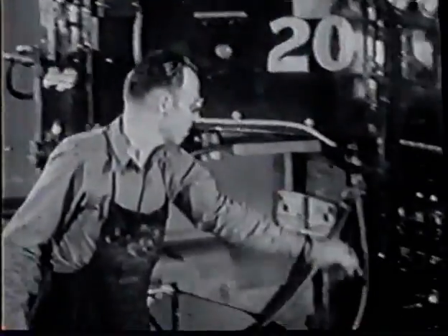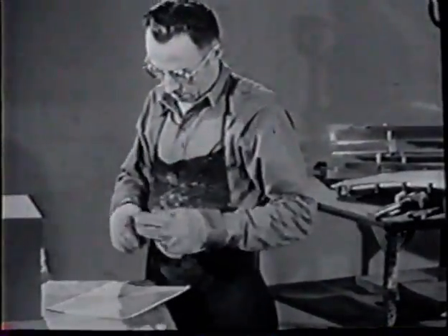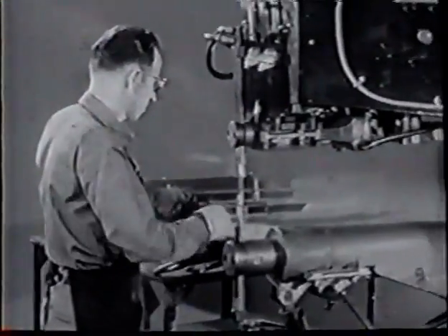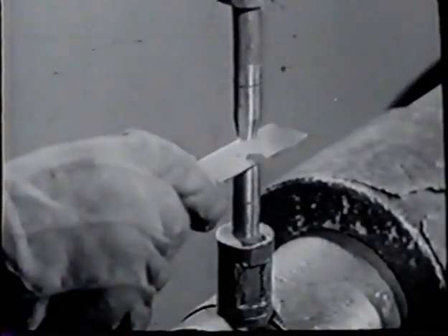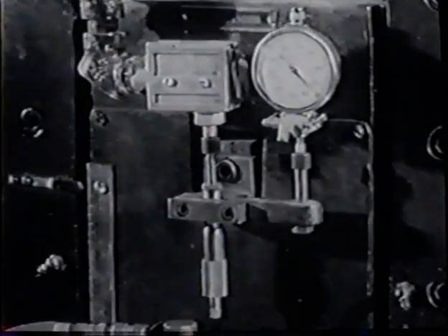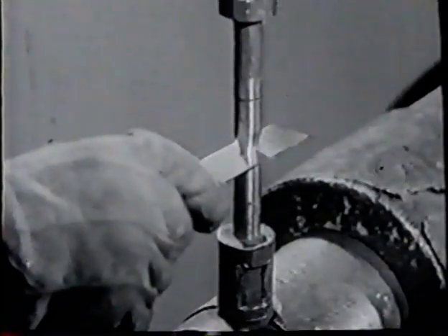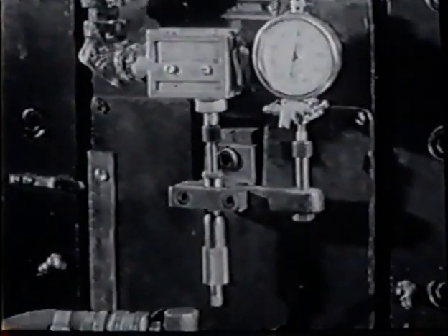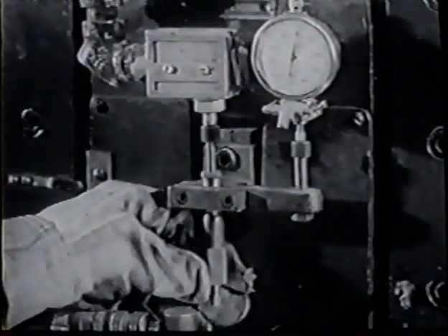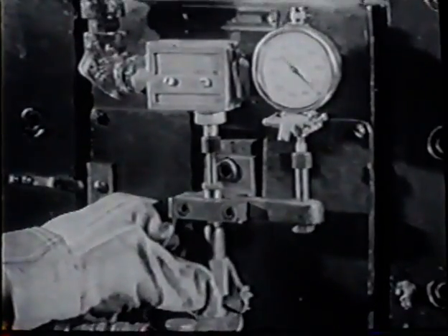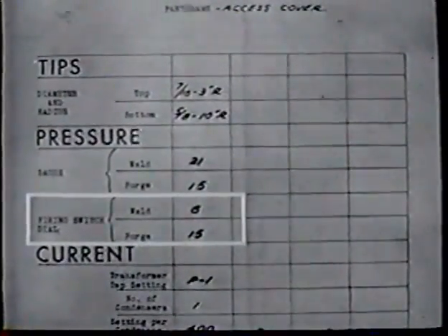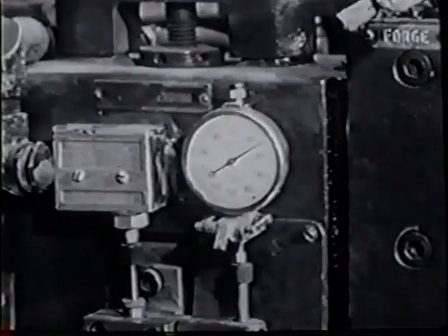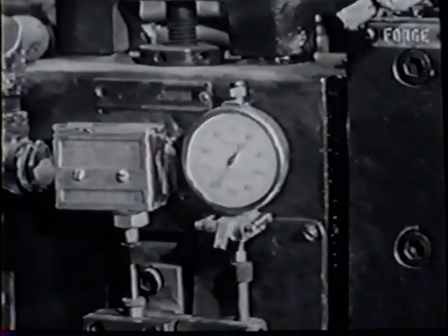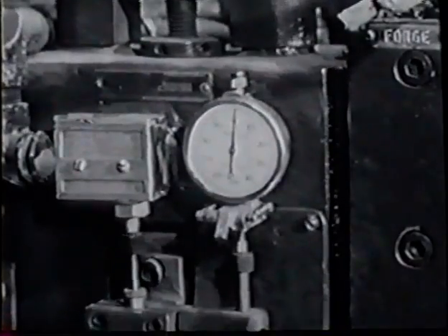Next, turn on the forge switch. Then, to get the exact pressure settings, put trial pieces between the electrodes and hit the pedals to exert tip pressure. Adjust the firing switch till weld pressure registers 6 and forge pressure 15. The dial hesitates at 6 and then jumps to 15.